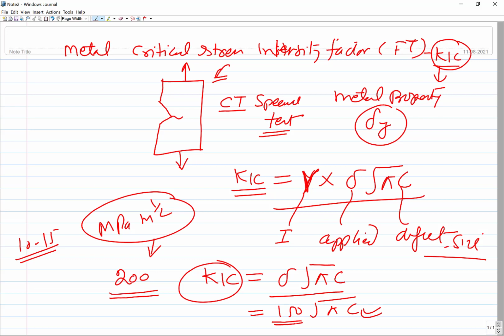Okay, when it is subjected to 150 MPa, then you can easily calculate what will be the size of the defect. Now, how do we calculate? See, it depends on where the defect is located, internal or external. For a defect which is external, located at the surface, that C is taken as equal to the defect size, and C by 2 when the defect is located inside, then C is half of the total length of the discontinuity. So the length of the discontinuity when it is present at the surface is equal to C, and the length is half of the length of the discontinuity when it is located inside.